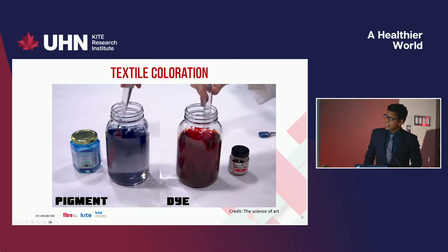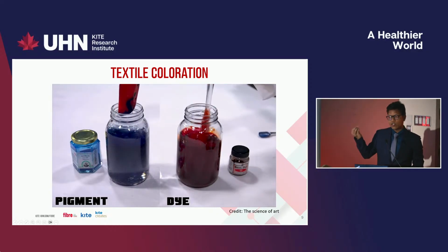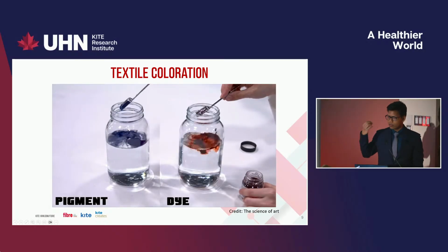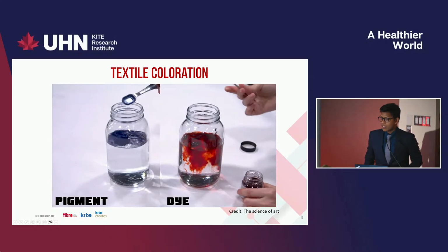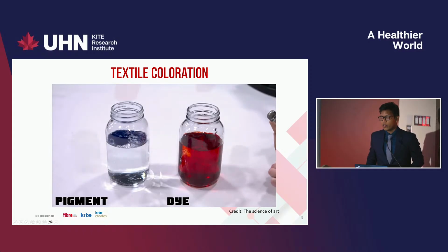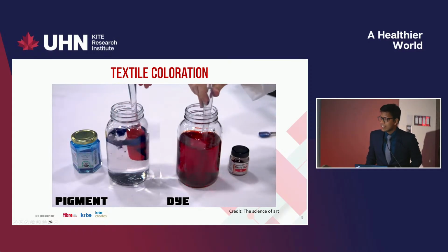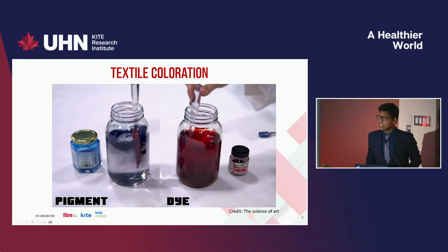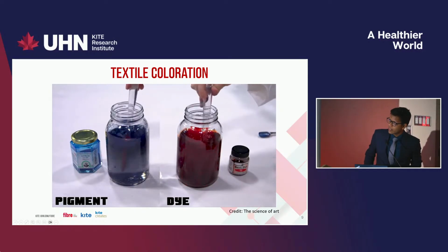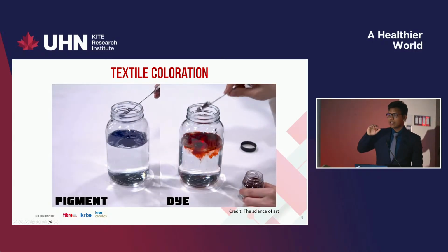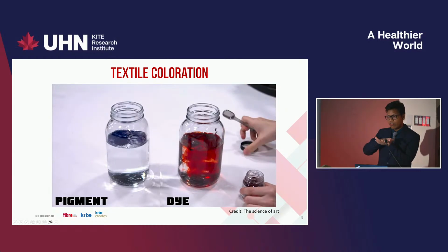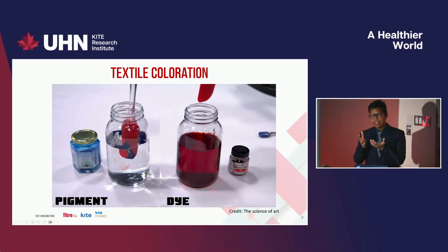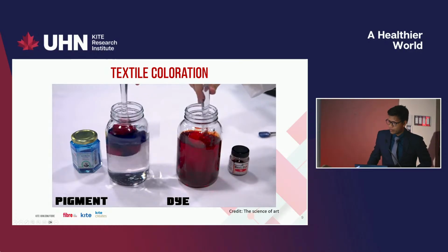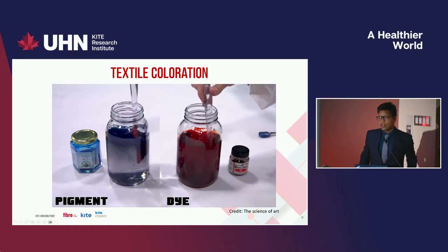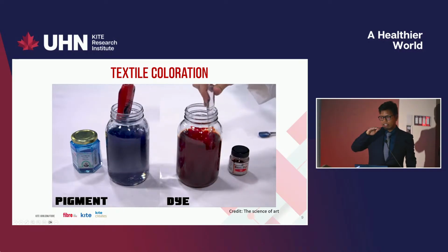For instance, for the dyes, as you can see, it's getting soluble, so it's easy to penetrate the fabric itself. We use other auxiliaries to make it bond well with the fabric, but in summary, dyes make very good bonding with the fabric. On the other hand, pigments, as you can see, are not soluble. While you put that pigment on the fabric as well, it doesn't bond with the fiber. So we use other auxiliaries, for instance, binder or glue or adhesive, in whichever term we say, to fix it on the textile substrate.